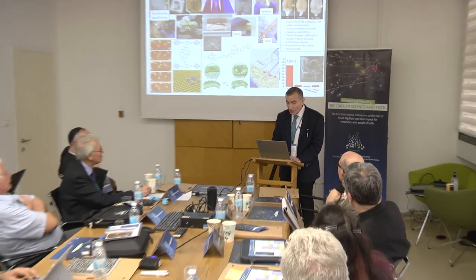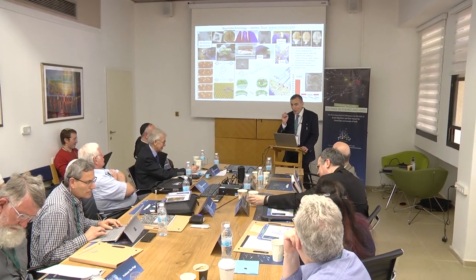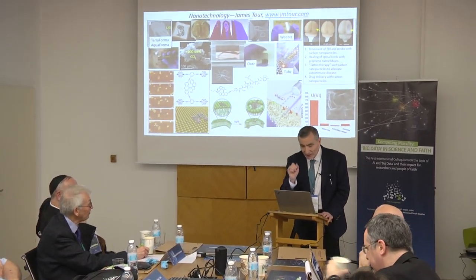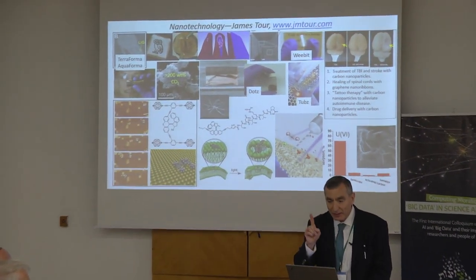We've learned how to grow graphene on copper foils using any carbon material, to show you could even do it from negative-value carbon material. What's a negative-value carbon material? This is the leg of a roach — you put a leg of a roach, heat it up to 1,000 degrees on the copper foil, you get very nice graphene. We wanted to show that we could convert anything into graphene at 1,000 degrees. Graphene is the thermodynamically most stable material based on carbon. The idea is that the value in something is not based on the price of the element, but on how those elements are arranged — that's what places value.